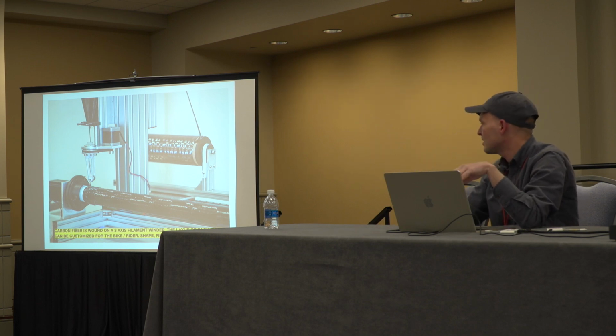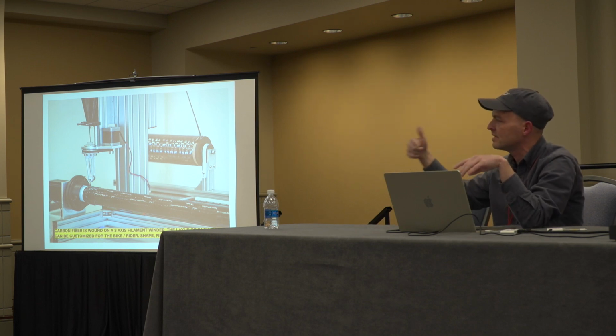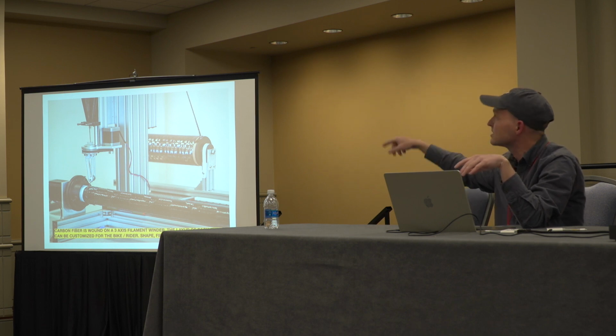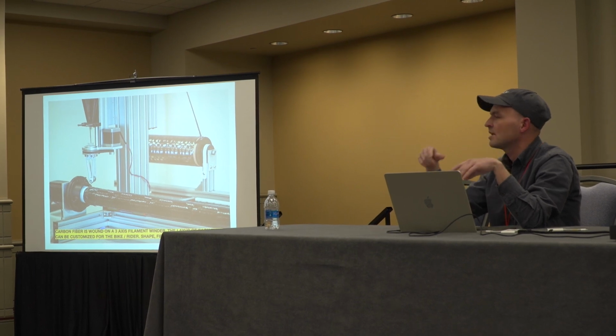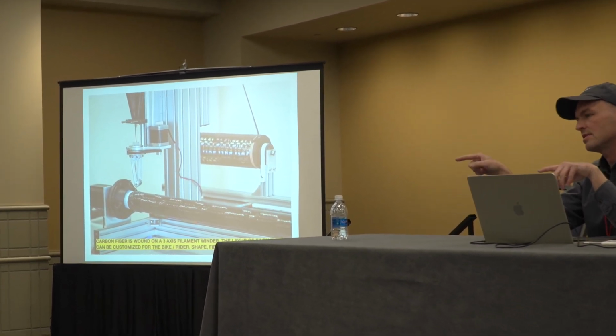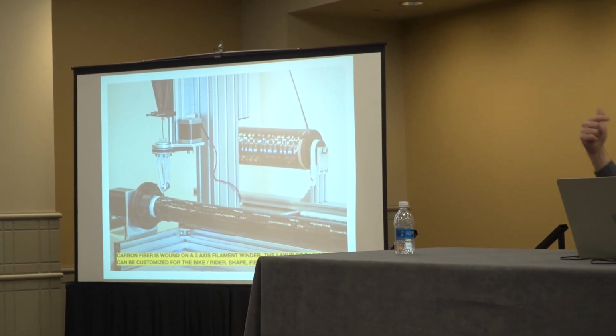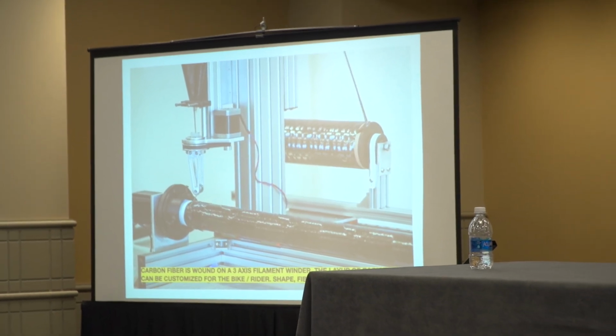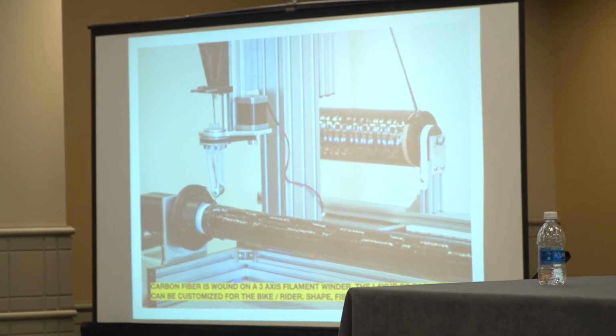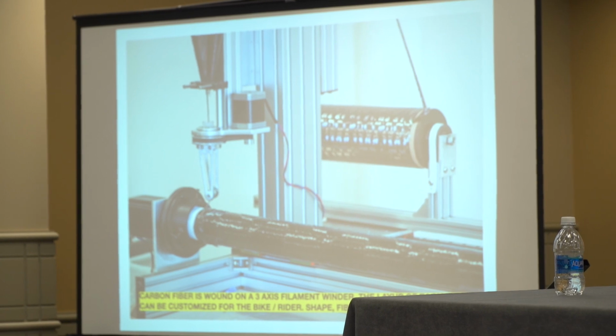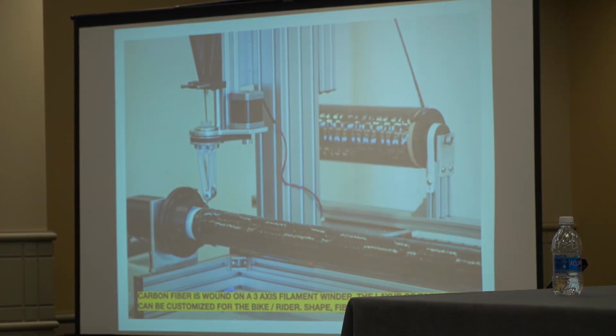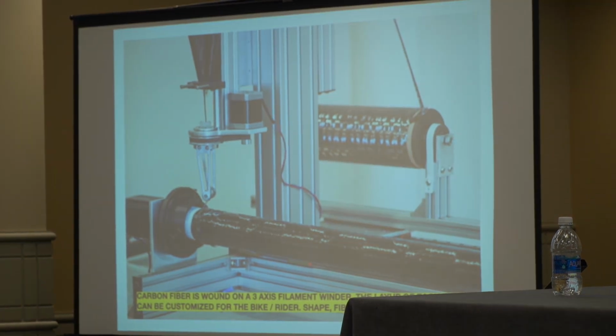Yep. And what's happening here, there's a dwell at the end of each tube. If you look closely at this image, it's a little hard to see because it's bright, but there's a bulb at the end of each tube. When it traverses and meets the end of the tube, it does an extra rotation or two, and it locks the fiber in place, and then it goes back the other way. So with a 45 or a 30, I can get away with just wrapping it a couple extra times to lock it in place. But if you go steeper than that, you have to catch it, and that gets trimmed.